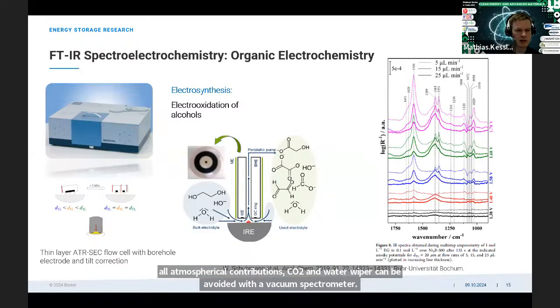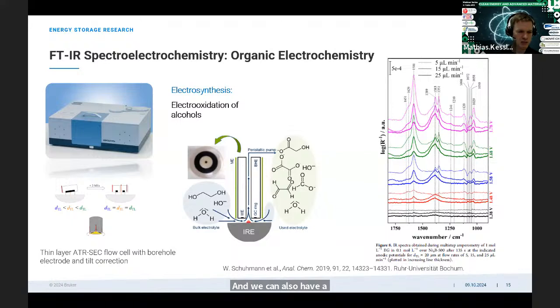We can also have a look at electrooxidation reactions. If we use, for example, a flow-through cell where the electrolyte is pumped through the electrochemical cell, we are able to do also ATR measurements on such a cell, and then we can observe the oxidation, for example, of ethylene glycol in the solution, and then we directly observe all the reaction products which will be created then. And we can then measure with different flow rates to optimize then our reaction conditions and to get the best results for that. So also such reactions with a continuous flow of our electrolyte, they are possible with the spectroelectrochemical FTIR cells.